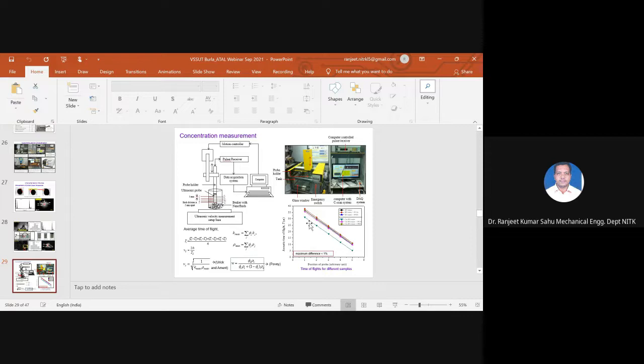The maximum difference of the time of flight between the successive positions of the probe is found to be less than 1% for each sample. We took initially DI water, then PBA solution, then PEG solution. Then we took the copper particles dispersed in DI water, then in PBA solution, in PEG solution. For all these samples, the maximum difference of the acoustic time of flight between the successive positions of the probe is less than 1%. After recording the time of flight at various positions, we calculated the average time of flight, that is Ts equal to this.